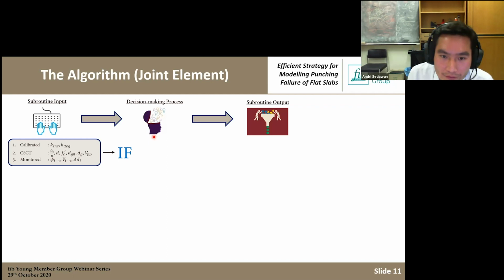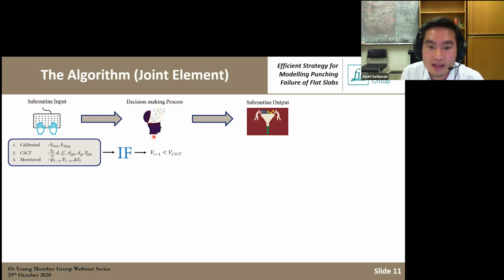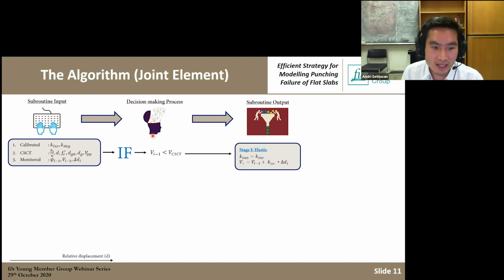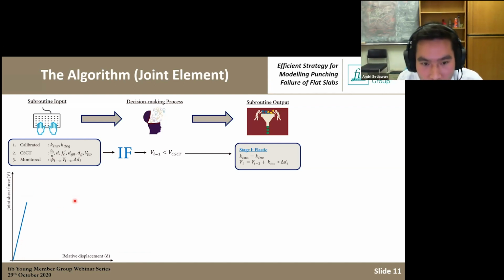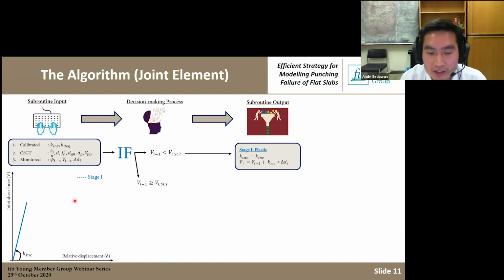The first if in the decision-making process is that if the joint shear is less than the critical shear crack criterion, this means that punching has not occurred yet. What happens is I'm just assuming an elastic behavior. You can see in the left bottom side of the slide, we have a linear response like that, simply a linear response without anything.